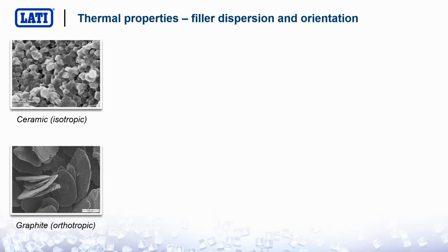The biggest issue when it comes to thermally conductive plastics is to properly disperse the filler. You have to be able to achieve an excellent dispersion of the filler inside, otherwise the compound will not work. The fillers are very different, not only for chemical or morphological reasons, but also from the shape they have. Ceramics are more or less always isotropic. They are like small spheres, as you can see above. Graphite and hexagonal boron nitride are flake-oriented particles, so they can actually orient during the filling.